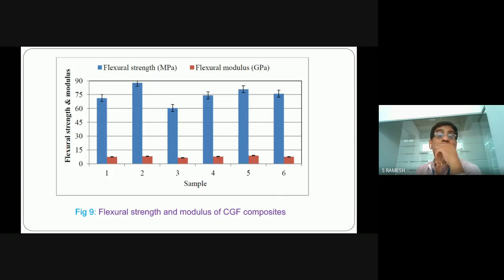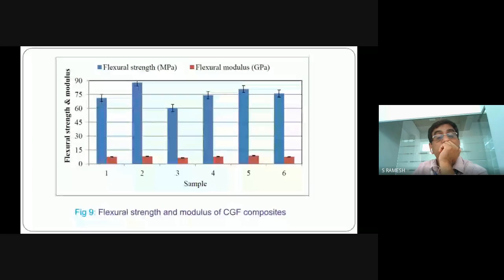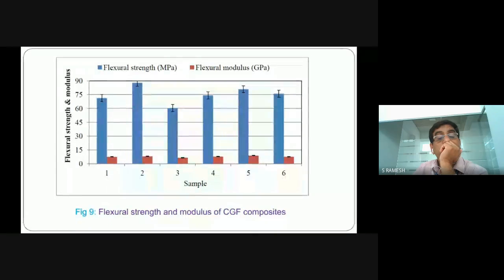First one is the flexural strength and the modulus of Calotropis gigantea bark fiber. Analyzing the figure, the flexural strength is taken from nearly 60 megapascal to 80 megapascal. Flexural strength is also known as modulus of rupture. We define it as the stress in a material just before it yields in a flexural test. From the figure, it is taken from 60 megapascal to 80 megapascal.